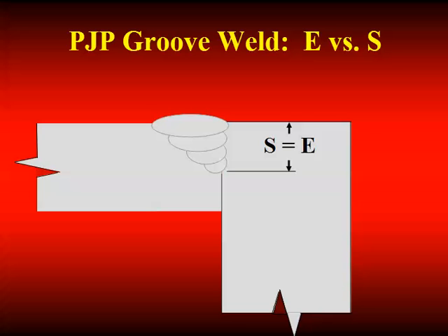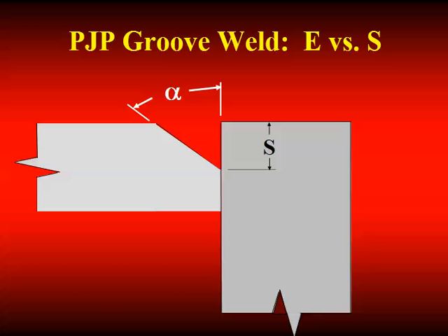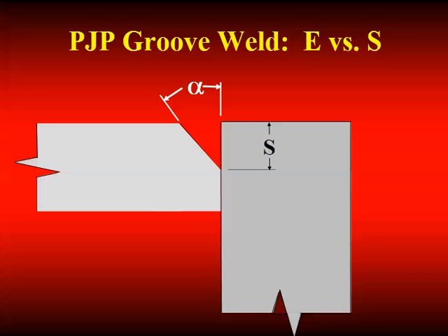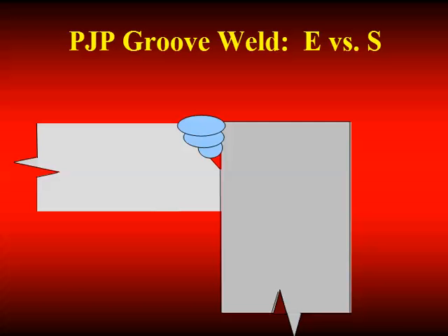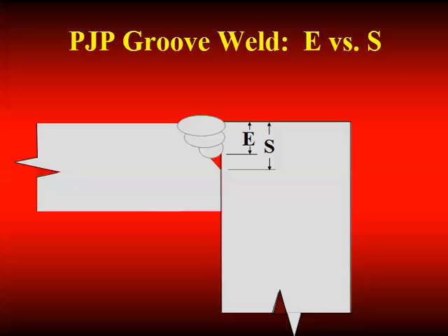Now, it's possible that I could reduce the included angle alpha and save some weld metal. If I reduce alpha far enough, I may not get fusion all the way to the root of the weld. Under these conditions, S is not equal to E. E would be the effective throat that goes down to the depth of fusion, but S and E are not the same.